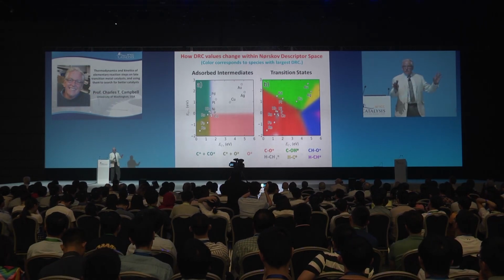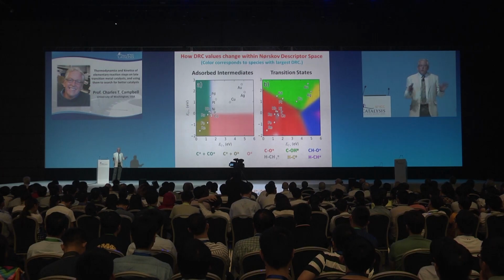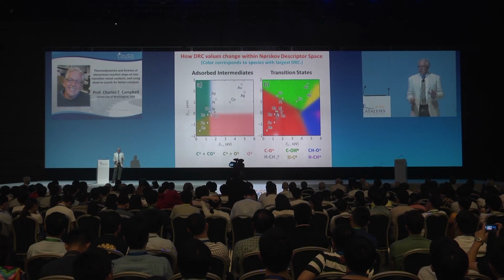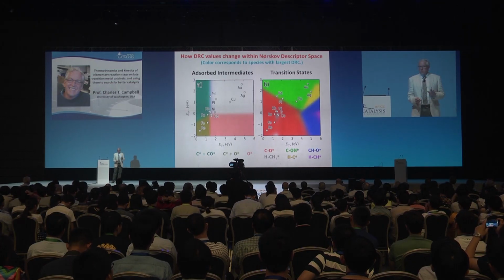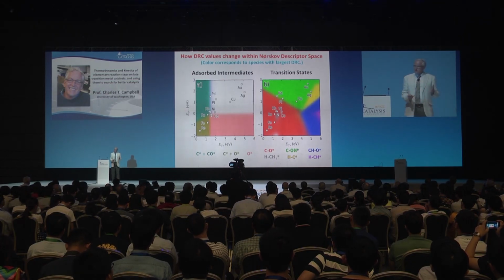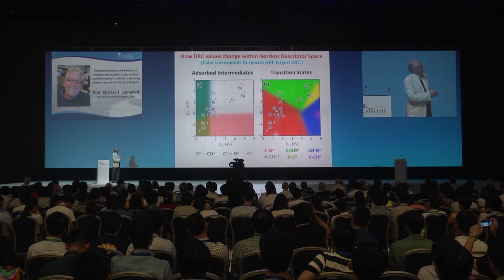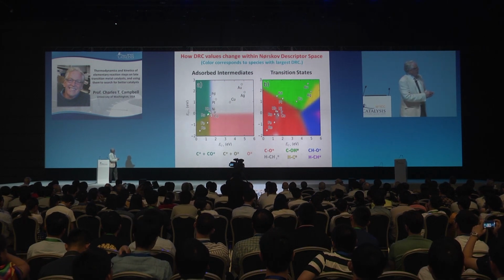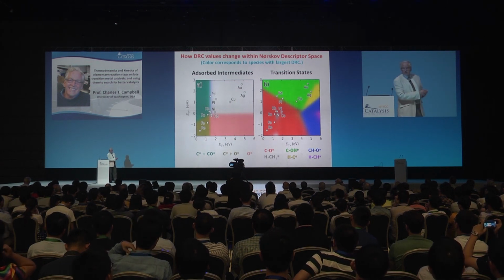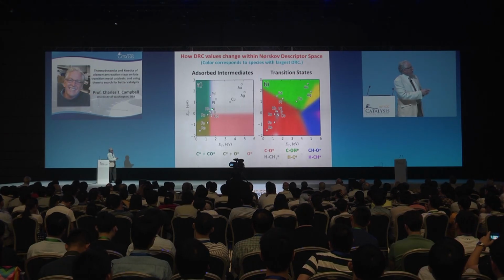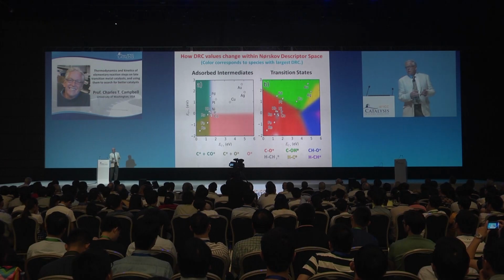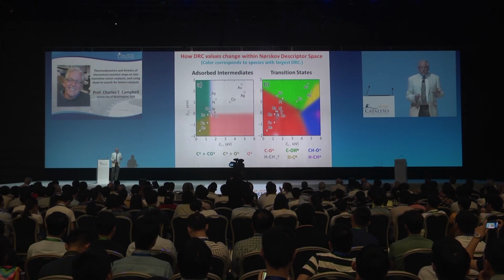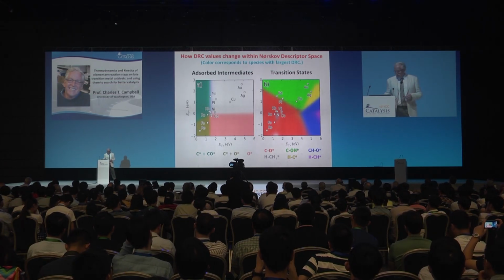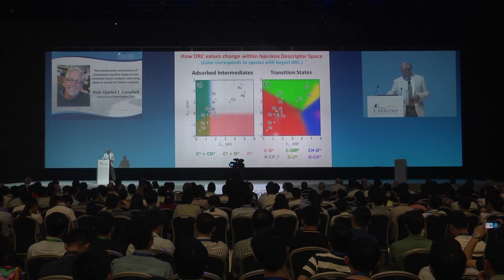If you look at that, you realize that there are huge regions in descriptor space or in material space where the degrees of rate control are staying constant. And so our method is accurate in regions where they stay constant. But we found that we got as good an agreement, if slightly better, than Norskov's method, even in this region, for species limited to relatively close, within 0.5 eV in descriptor space of the reference material.